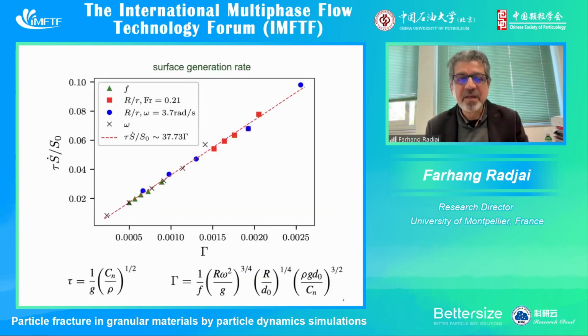And in the end, by investigating all the individual effects of these parameters, we were able to find a scaling parameter, gamma, which is shown here, in which S dot is the rate of surface generation compared to the initial value, and tau is a time, which depends on Cn, which is the strength of the particles, rho, their mass density, and g is the gravity. And a combination of Froude number, size ratio, and another ratio, which is the ratio actually of the weight of the particles to the strength of the particles. And with non-trivial exponents here, as you can see. And we can collapse all the data on a single line. This was done only for the cascading regime. So it is valid only for the cascading regime. When we leave this regime, this scaling doesn't work anymore.